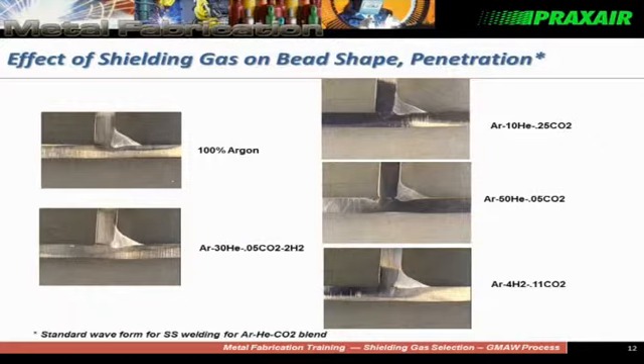And just, again, to show you what some of the shielding gas can do. This is all done under similar welding conditions. You look at different bead-shape characteristics you get by just changing some of the gas blends. Different penetration, different surface characteristics. Some are flatter. Looking at just the cross-section, you don't get a full picture of what the weld bead looks like. Like this argon looks pretty good, but actually the surface is fairly rough if you looked at the surface of the weld bead. But again, the shielding gas affects some of the characteristics of the welding process.